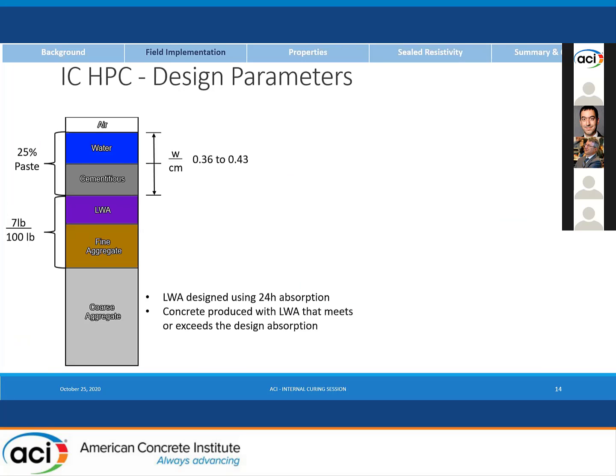For the mixtures that we were implementing, we were looking at a 25% paste volume, a water to cementitious ratio anywhere between 0.36 and 0.43. I believe everything was about a 0.40 for this study. We're providing at least 7 pounds per every 100 pounds in terms of internally cured water. We were following a little bit of a modified approach, so it's not exactly the same as 1761.